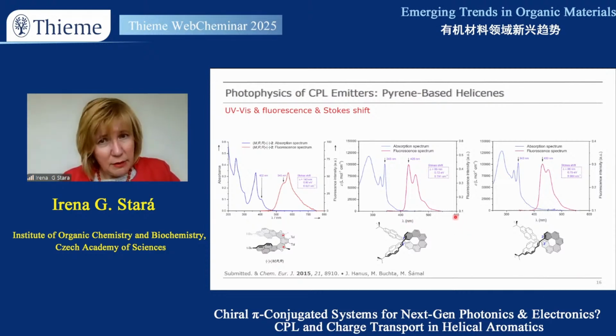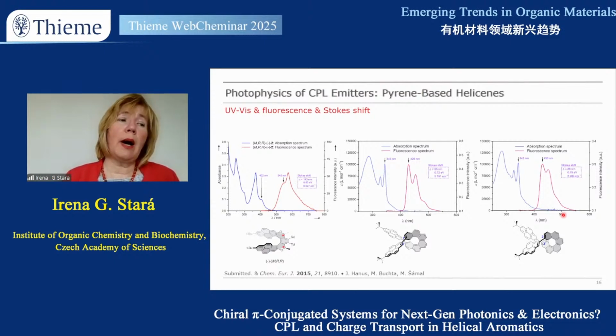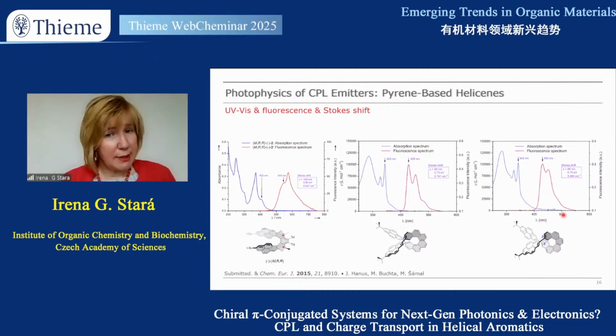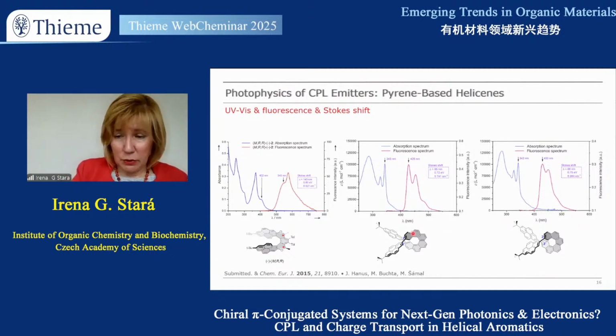The completely different situation is in this picture and this picture, meaning that pictures of C2 symmetric compound, C1 symmetric with only sigma bonded structures. And here you can see that the band which would be described as excimer band is missing. So it confirms what I said. So now we are trying to rationalize our observation, because it's obvious that the commonly accepted explanation for high CPL properties is usually combined with the possibility of formation of internal excimer, but here it's not the case. So we are working on it.